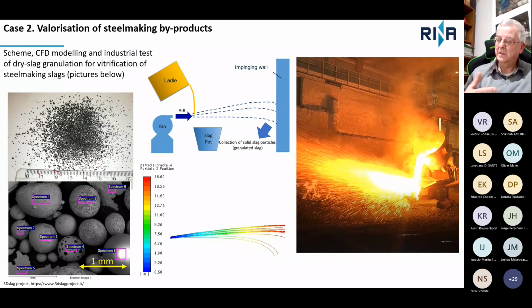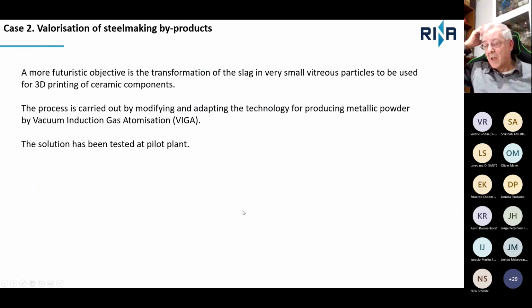And as a first example, the dry granulation of the slag, which is a technology solid enough for blast furnace slag, but not so developed for electric furnace slag. The dry granulation can produce materials that could be used for more applications inside the steelworks or in external environments, for example, for scaling or other activities. And this is an example of the dry granulation of the slag.